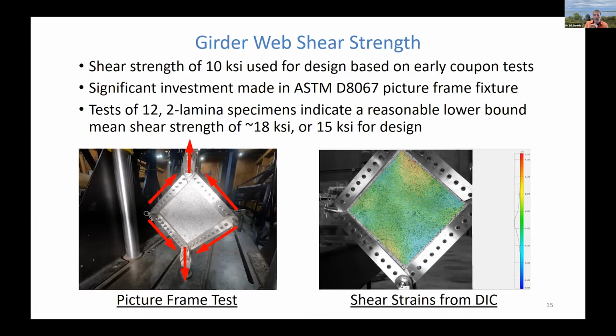That was based on some early coupon tests according to an ASTM standard that really isn't designed to assess the in-plane shear strength of foam core panels. I should point out that 10 incorporates a knockdown factor of about 0.85 to account for statistical strength reliability. So the mean shear strength would be somewhat higher than that, but the design value is 10.